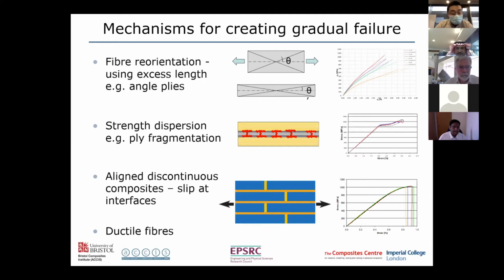And we also looked at aligned discontinuous composites, where we can get slip at the interfaces, which can create additional strain. And the HiPerDiF program, which was mentioned yesterday by Enrique, the HiPerDiF method for aligning short fiber composites, came from this program. It was originally developed to create these pseudo-ductile responses and to look at hybrid materials. But we found it was a very effective method for producing materials with just one fiber, and particularly giving the ability to use recycled composites.